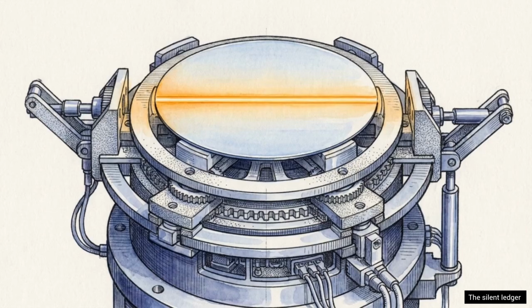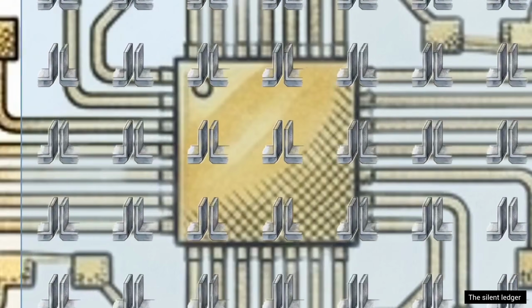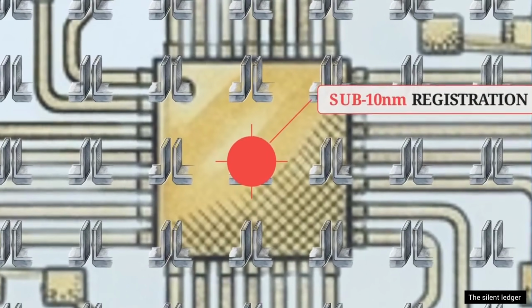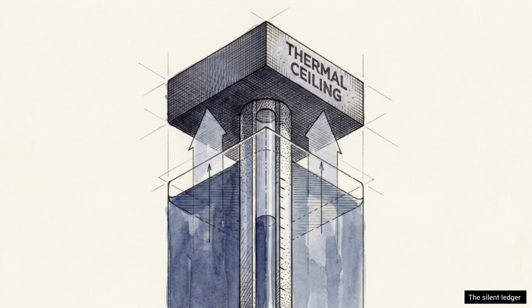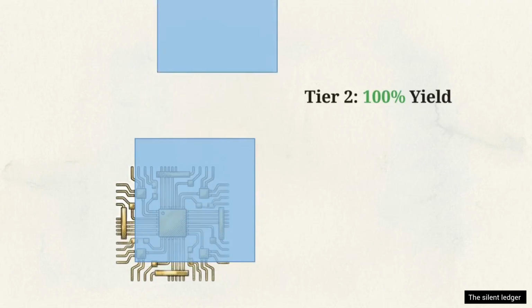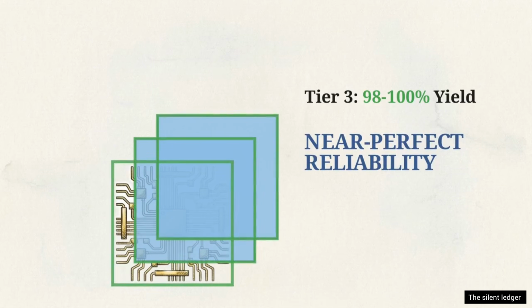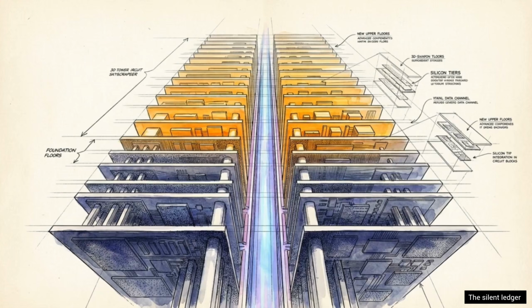The laboratory metrics proved the concept. They achieved sub-10 nanometer alignment between tiers, processed safely under 400 degrees, and hit device yields of nearly 100% across 3 stacked tiers. By redesigning the transistor to match the ultrathin membrane, they successfully stacked high-performance silicon without melting the existing floors. If monolithic 3D integration reaches commercial manufacturing, it shifts chip design from a flat layout geometry problem to vertical architecture optimization.